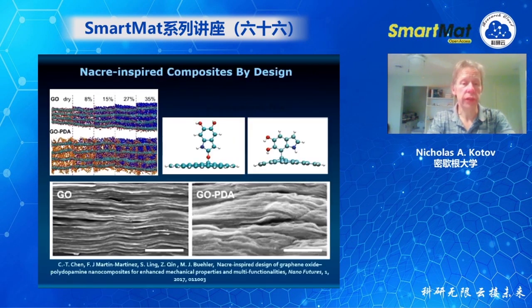So with that knowledge, we can also establish some computational means. And I think this work by Markus Buehler at MIT demonstrates very well that LBL assembly from graphene oxide and PDA is very simple and very conducive to the computational description because each layer, each interface is reaching the equilibrium, and that leads to exceptional cohesion at each interface, and thus to